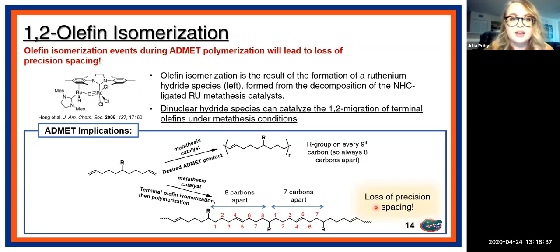Another thing to consider is the presence of 1,2 olefin isomerization. So these isomerization events during ADMET polymerization are another cause of loss of precision spacing. The reason why it happens is the formation of ruthenium hydride species that look like this. So this is a decomposition product of N-heterocyclic carbene ligated ruthenium metathesis catalyst. And this dinuclear hydride species catalyzes 1,2 migration of terminal olefins under the same conditions that metathesis occurs.